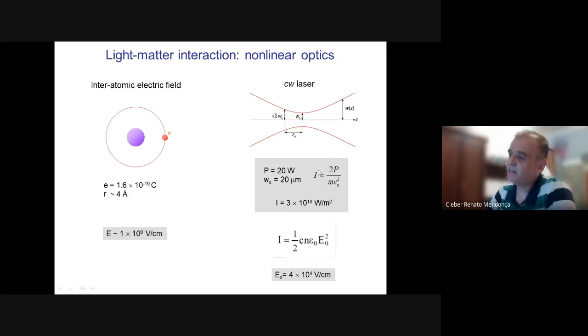Then if you calculate the intensity, you get something on the order of 10 to the 10 watts per meter squared. And then you use the Poynting theorem. You plug in the intensity, and then you calculate the electric field of your laser. And then you get something which is 10 to the 4th volts per centimeter, okay? So as you can see, even if I focus this 20 watt laser, which can be used to cut metal, very tightly, still you don't have enough intensity to get to the interatomic electric field.